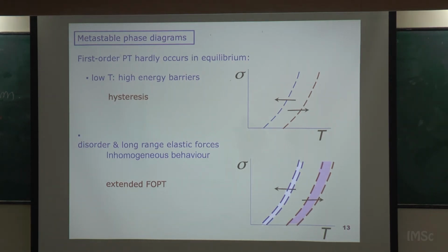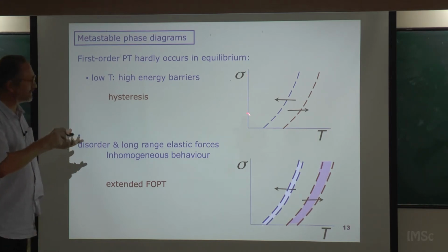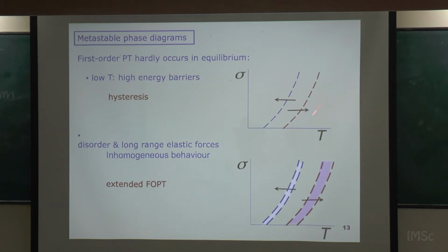So this is now for structural phase transitions. This is applied stress, this is temperature. You have a line like this that separates the two phases, but this line is different. When you go from low temperature to high temperature, you have the red line. But when you go from high temperature to low temperature, you have the blue line.